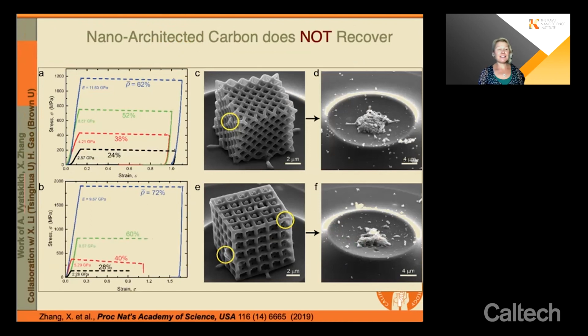In the hollow nanolattices, they deform and they're able to recover by a process called shell buckling. Imagine your soda can. This shell buckling allows the material to spring back after corrugating it, effectively. That kind of instability is an elastic instability, and so it allows the material to fully recover to its original shape. In contrast, in the carbon nanolattices the beams are not hollow, so they don't have that mechanism of recovery.